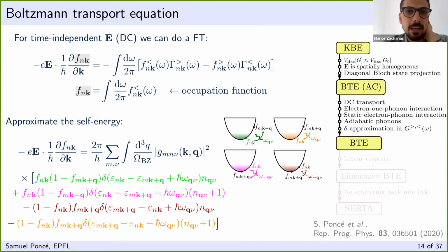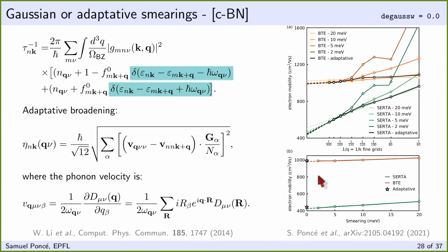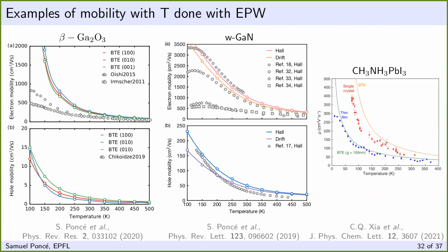So I think, Samuel, we have time for a short question maybe from Mao Yang. Thank you for your talk. I have a question about the result for perovskites on page 32. To calculate the relaxation time of perovskites, is the Debye-Waller term included, and does the Debye-Waller term contribute more than the Fan term in perovskites? Because yesterday you showed the temperature dependent gap of perovskites, and the high order term contributes more, so the band gap can increase with temperature.